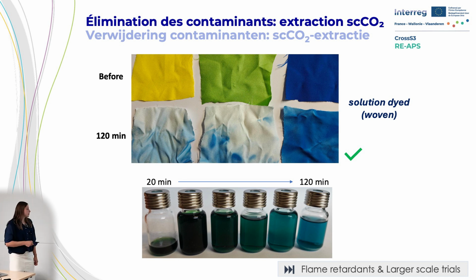And also the extract, so that's what I mentioned before, that the extract in the first time was not so much. We see that it starts very dark, but still at 2 hours it's quite blue. So we think that by extending this trial to longer times, maybe we can also de-ink the blue solution dyed woven textile more. So next steps are we want to expand the trials that we did, for example, go for longer times for these materials.